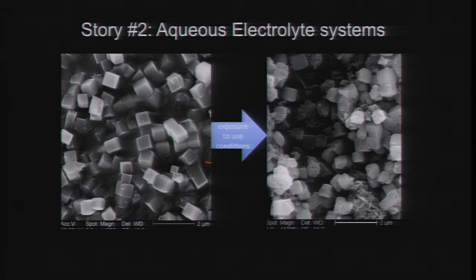One of the things that we do is we create model systems. This is a model system of an anode material. This is sodium dititanium triphosphate. It's a mouthful, but what for this audience matters is that I can make really nice, almost perfect cubes of this material. And why I like the perfect cubes is that it gives me very flat facets and corners. So we have a really good sense of the uniformity and what this should look like if nothing goes wrong with it.